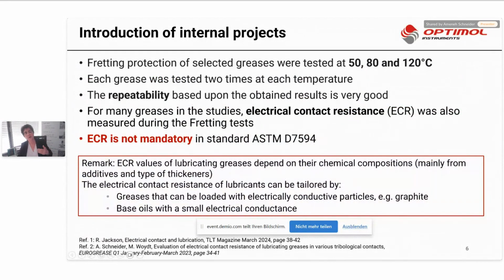Now we go through a little bit, introduce you about our internal project, which I can go to more details about. We had many different greases. We tested them at different temperature, 50, 80, 120 degrees Celsius, and we have done all the tests 2 times. Repeatability was given for all of them, as I mentioned before, and we added electrical contact resistance sensor for some of this project, not for all, for some of them, but it should be mentioned here that this measurement is not mandatory in this standard. Why we add it?